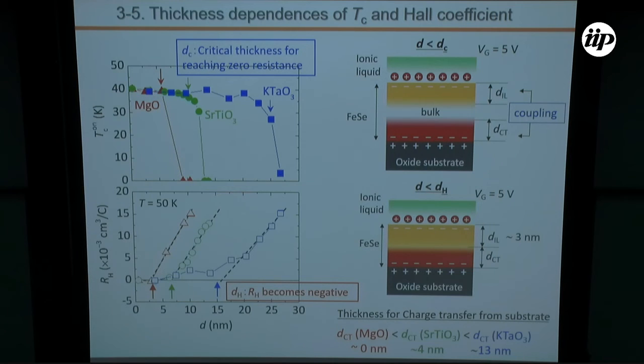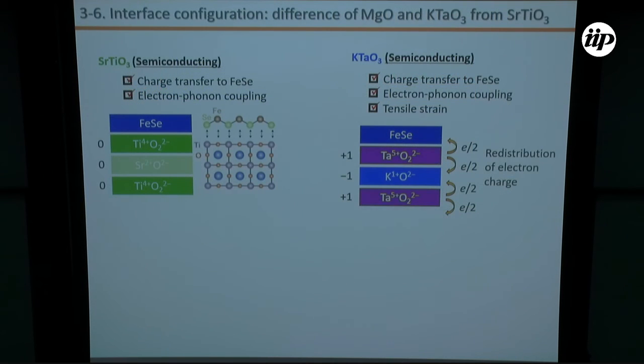And this difference in substrate can be explained by the interface configurations of the three kinds of substrate. In the case of strontium titanate, oxygen defects on the top surface cause electrons, and these can transfer to the iron selenide. This is the origin of the minus Hall coefficient of the high TC superconductivity.